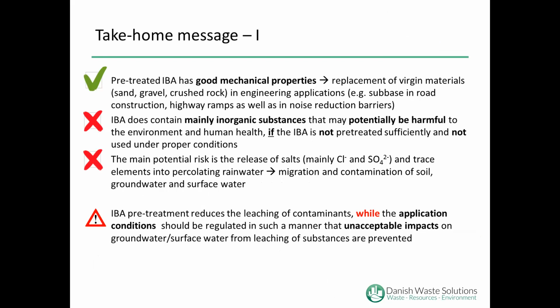However, bottom ash also contains inorganic substances that may be harmful to the environment if they leach out, meaning the bottom ash needs to be treated sufficiently and used under proper conditions. And the main potential risk is related to the release of salts and trace metals into percolating water, thereby polluting the groundwater.